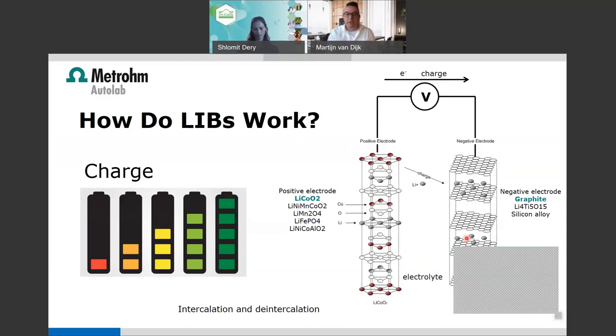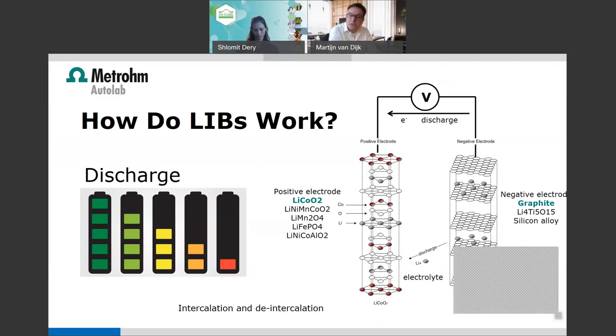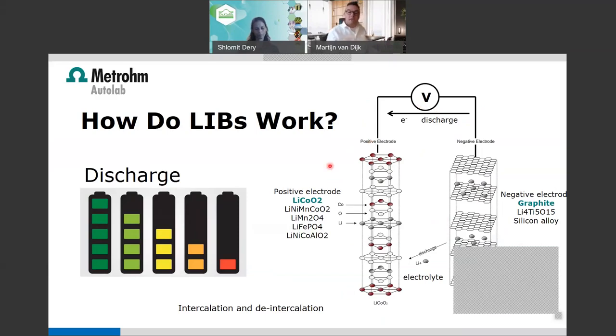During discharge, when the circuit is closed, thermodynamically the discharge reaction is favorable: lithium ions move from the anode and intercalate back into the cathode to their initial state. At the same time, electrons move in the same direction — from anode to cathode — and are consumed by the device (e.g., your cell phone). Essentially, charge and discharge is just the shuttling of lithium ions back and forth between the anode and cathode.